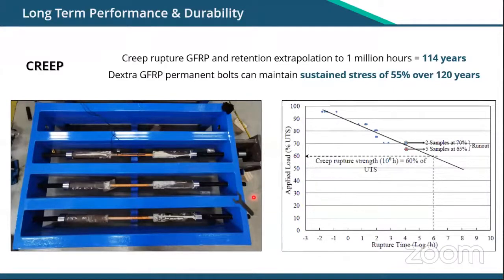We characterize it, the picture you see is a test performed by Dextra with a third-party partner. There's again an ASTM and ACI standard. We perform long-term stress of those bars at different percentages of the UTS. So again, if you stress it at 100% of its UTS, its ultimate tensile strength, you would get immediate failure. However, if you stress it, as we can see on this graphic, at a lower percentage, the failure will occur later. And please mind the scale here. It's a logarithmic scale. And again, here what we care for, with a permanent structure, is probably the 10 to the power of 6, the million hours being 114 years.